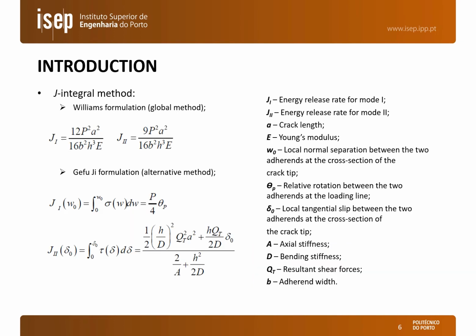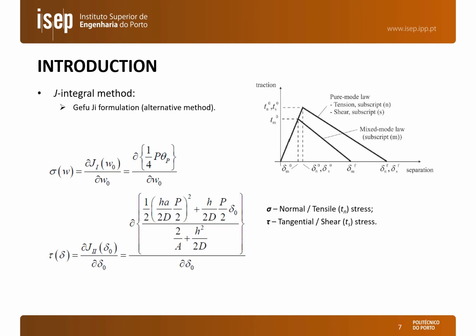We are going to test two formulations. One is the Williams formulation, but we are going to focus with a higher preponderance on the Gefu Ji formulation, which is a J-integral formulation, which allows us to obtain G1 and G2 as a function of the tensile and shear openings of the crack, and then to obtain the cohesive laws by differentiation. As I said, we can obtain the sigma-w curve, which is the tensile cohesive law, by differentiation of the G1-w0 curve, and the shear cohesive law, which is the tau-delta curve, which is obtained by the differentiation of the G2-delta0 curve.